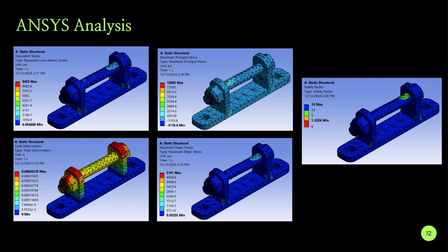And then for our analysis and results in ANSYS, we found that our von Mises was actually around 9,453 psi with a shear stress of 5,141 psi, and that gives us a factor of safety for fatigue at 1.3, which is much more accurate.